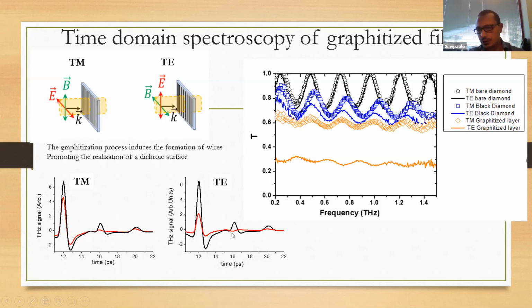This change in the reflection is a clear fingerprint that when the polarization is TE, so when the electric field follows the directions of these wires, graphitized wires, we are measuring something that is almost metallic. A metallic layer provides a pi shift in the first reflection because epsilon is negative. Instead, when it's TM, it's like an insulator. Okay, we have summarized this information studying the modulus of transmission.